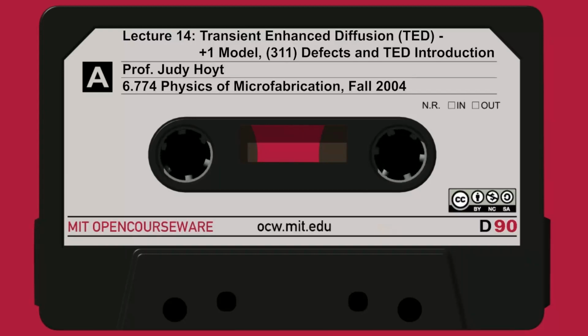So we write a simple differential equation. Time dependence depends on a growth term minus a shrinkage term. Now this is a little hand wavy, but in your text we talk about how this forward reaction rate is believed to be diffusion limited. So the interstitials have to diffuse into this cluster. In fact, they're created throughout the crystal, but they have to diffuse into the 311 cluster. So we usually say that this forward reaction constant K sub F is proportional to some nearest neighbor distance A and an interstitial diffusivity D sub I. So at least we know what kind of parameters go into that. So that's what we write for K sub F.